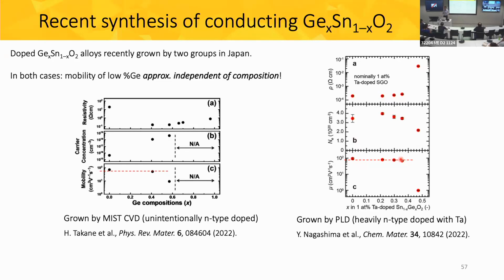So even though there's a random arrangement of germanium and tin atoms, where you would expect the mobility to tank because of this alloy disorder, we see the mobility is insensitive to the composition. So we're doing work to understand why exactly this is happening. How does the interplay of phonons with alloy disorder give rise to this apparent insensitivity of carrier transport to disorder?